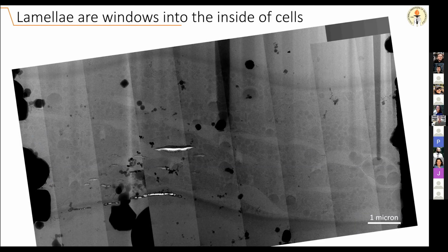And so then these lamellae can be observed by CryoEM. And so here I show a lamella of a pollen tube, and you can see that when we erode away above and below the lamella, we're left with a thin vitreous sample where we can do tomography. And here we can see all the insides of the pollen tube in a near native state.